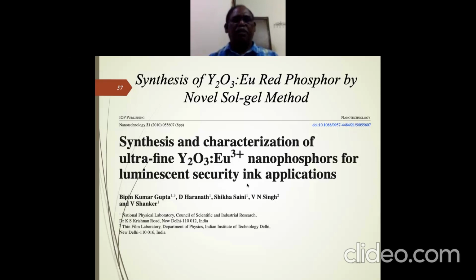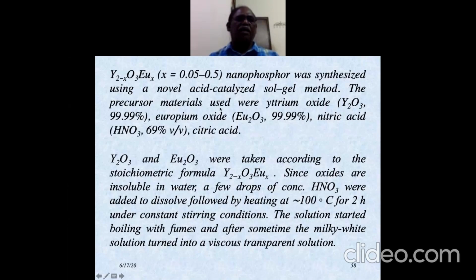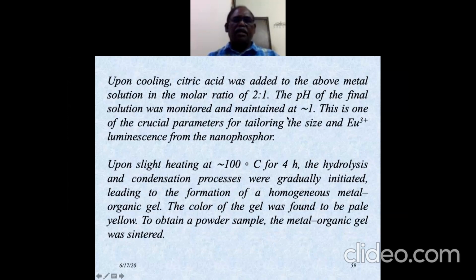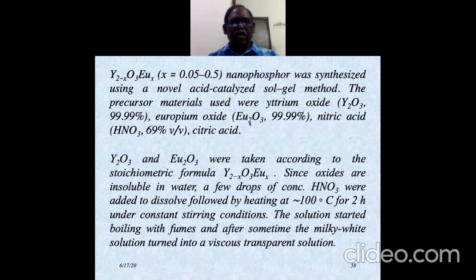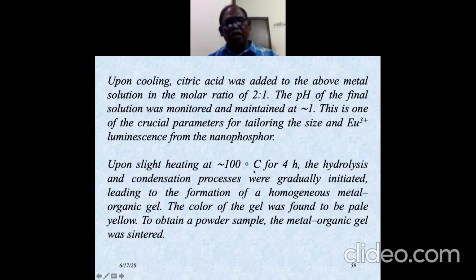So they have prepared this by a simple, again, sol-gel method. They dissolve the oxides, both the impurity and the yttrium oxide, in nitric acid and a small amount of water, and then form a solution of that. And they say the pH of the solution is very critical in tailoring the size of this particular phosphor, and then they use citric acid as a gel. So the gel is formed. Then by sintering this gel, you get this kind of nanoparticle.